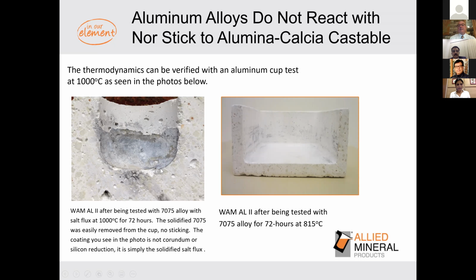And again, this test is done at 1,000 degrees C, which is extremely high temperature. And you can see that, again, the calcia is not reduced. There's no silica to be reduced, and subsequently, you have a refractory that is not attacked by molten aluminum.